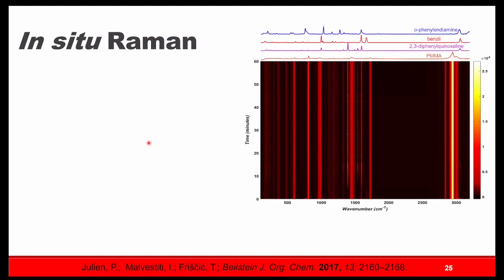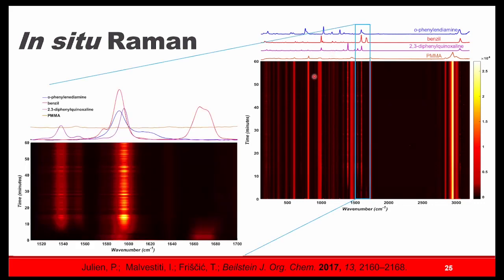We can look at that now using Raman spectroscopy. Again, these are plotted using waterfall plots. The idea is going to be the same. We have a lot of background due to our PMMA jar, which we're using. So we can get the Raman signal of the reactants when they're not in the same place as the PMMA bands. We usually find a region where we get good Raman signal of all of our reactants, and we don't have a lot of interference from the PMMA, and we're able to actually get this Raman signal.